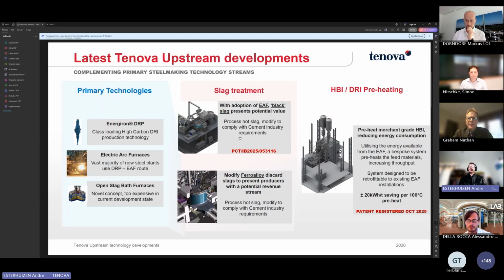And then I just want to say that, again, we know that HBI is an important hub, especially in the Middle East. We know that the HBI produced in the Middle East, because it's the best place to produce HBI in the world at the moment, allows us an opportunity to add a complementary technology to the electric arc furnaces so that we can improve the performance of an electric arc furnace. If we preheat the HBI, for every 100 degrees we do so, you get a 20 kilowatt hours per ton saving on the performance of the EAF.